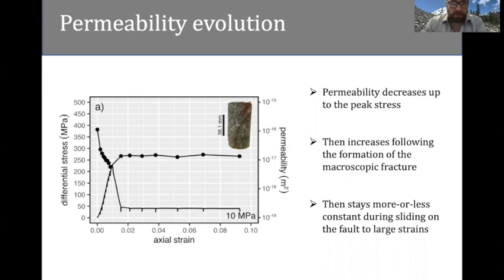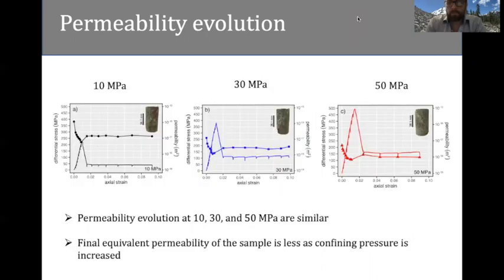And then as the strain is accommodated by frictional sliding on the macroscopic shear fracture, we see that there is more or less no change in the permeability of the sample up to the maximum strain of about 10%. So here are the permeability data, or the permeability evolution as a function of axial strain, for all